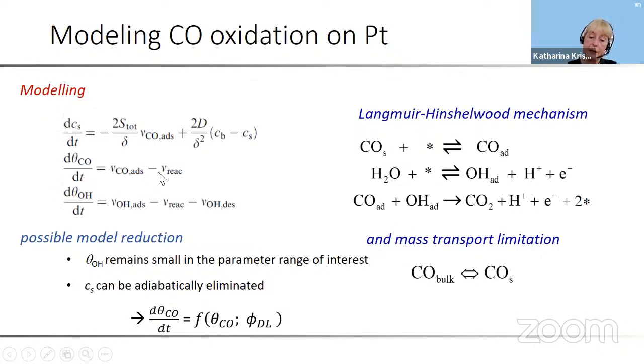variables, 3 coupled ODEs. But when you are only interested in the mechanism that creates the positive feedback, and in a simple variation, you know that you can always reduce your system of equations to a single equation. In our case, the coverage of OH remains always small in the parameter range of interest. So we don't need really to take this into account, and we can adiabatically eliminate the concentration in front of the surface.